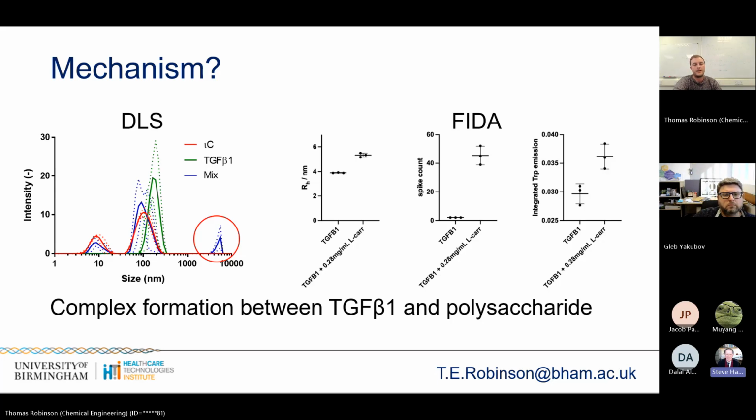We've got a little bit of data from a technique called FIDA, which is flow-induced dispersion analysis, which, if you're a chemical engineer like me, is a really interesting technique because you essentially shoot your sample down a pipe. It then forms a parabola, but the diffusion out of that parabola, both backwards and forwards, then obviously depends on the molecular weight.